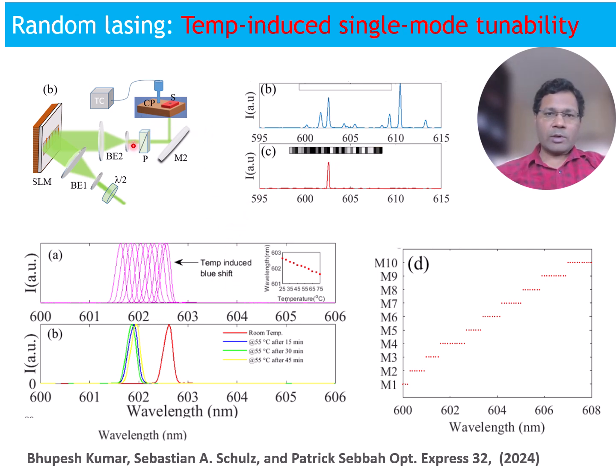The random laser sample was mounted on a copper plate with a rectangular aperture that allows pumping from the bottom, and the copper plate was thermally coupled to a heating probe for controlled temperature variation. Due to thermally induced changes in the refractive index of the polymer, we observed a blue shift in the lasing spectrum, as you can see in this figure, as the temperature is increased. Specifically, each 5-degree rise results in a 0.1 nanometer shift in the wavelength. Over a temperature range from 25 degrees Celsius, that is room temperature, to 75 degrees Celsius, we achieved a total shift of 1 nanometer for each single mode individually selected. With this, we can tune any individually selected mode by 1 nanometer by just changing the temperature.